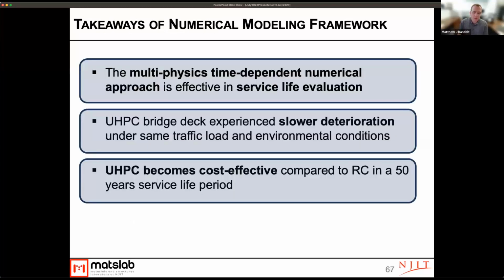So some takeaways from the numerical modeling framework. First, the multi-physics numerical approach gives us an effective way of predicting service life evaluations. The UHPC bridge deck had slower deterioration, and a companion study that our colleague Hao Wang helped us with, which we didn't get into the results of here, showed that when you look at actual dollars, UHPC was a cost-effective solution compared to the RC system in a 50-year service life. That's in our actual technical report, but not within this presentation, just due to time constraints.